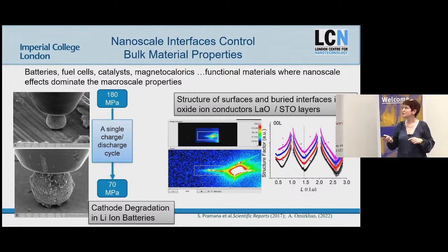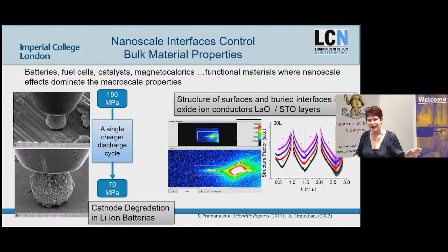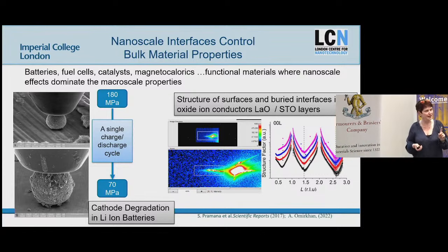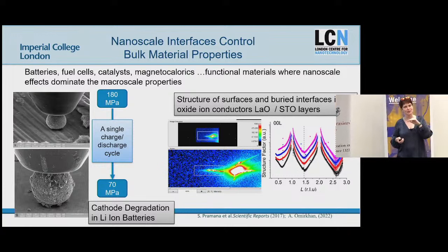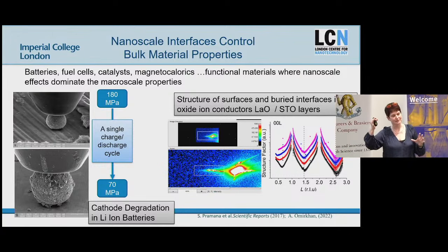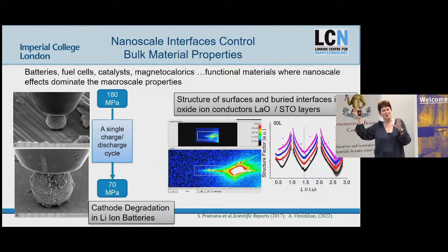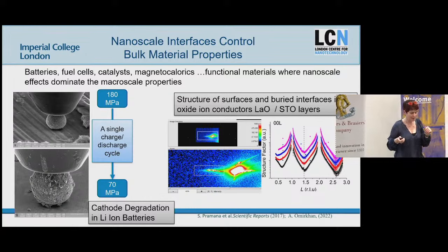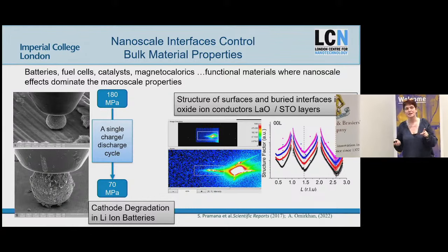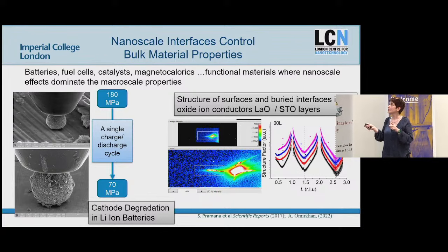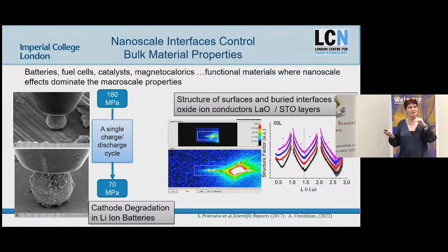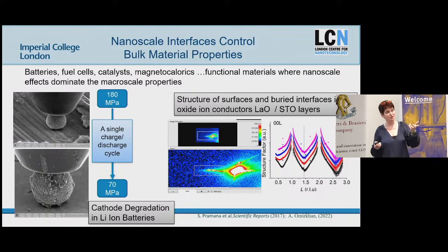And if you've been taught about diffraction, you'll have been taught that you've got a Bragg condition, and when you satisfy the Bragg condition, you'll get a peak, and then you'll get nothing, and then you get a peak, and then you get nothing. Not true, right? Because actually, when you put a surface or an interface in your system, and you get your geometry right, okay, and this required us to do really hard reciprocal space, six-circle goniometer experiments. I'm putting it up here because it's a really hard experiment. What you find is there is intensity between the Bragg peaks, and this comes from the surface or the interface scattering. Right? And so if you measure non-zero intensity between the peaks, that tells you something about your surface, and that's really important for understanding surface structure, surface dynamics.